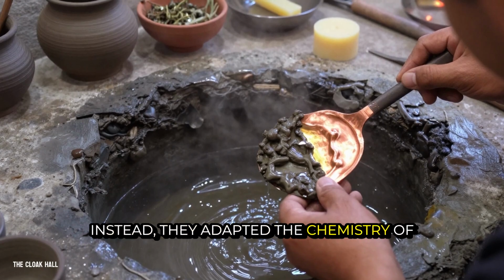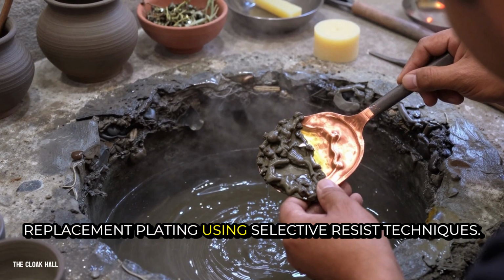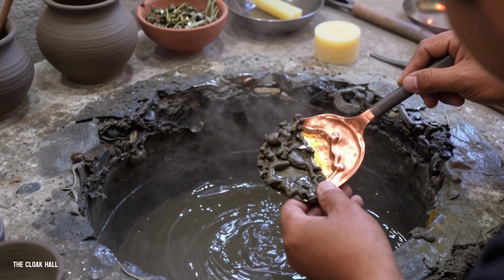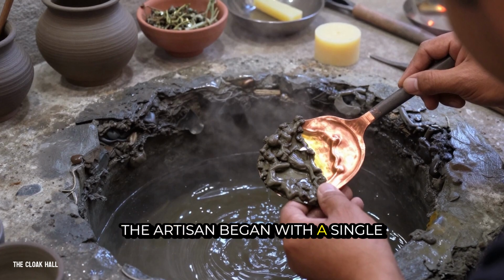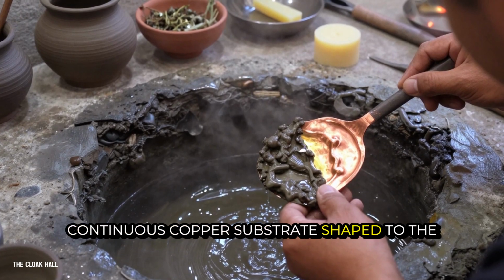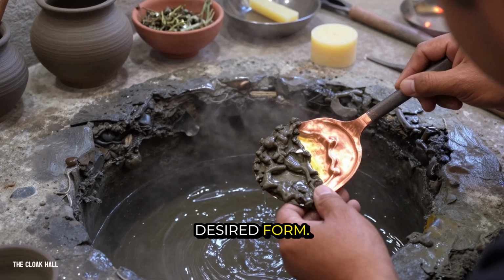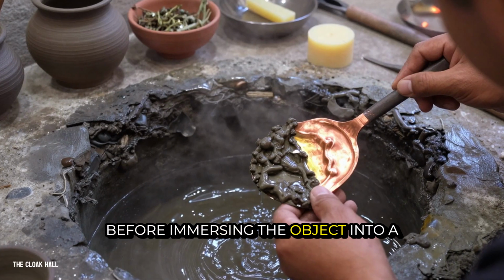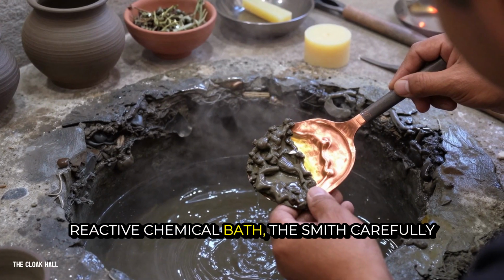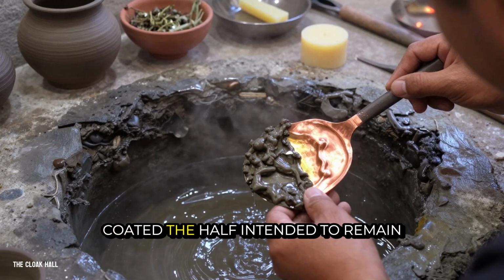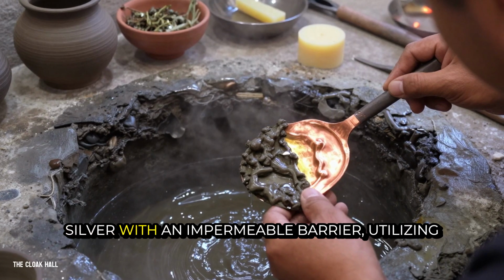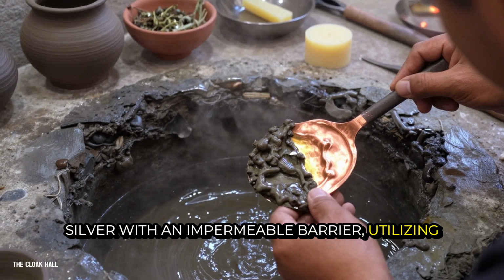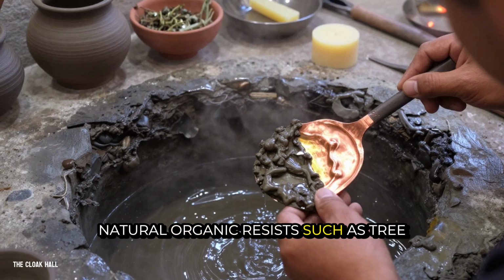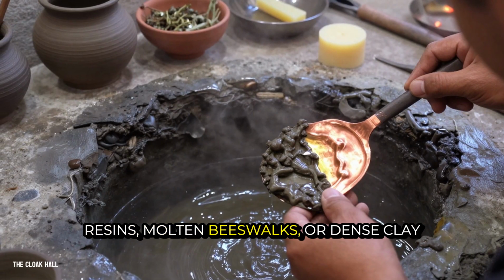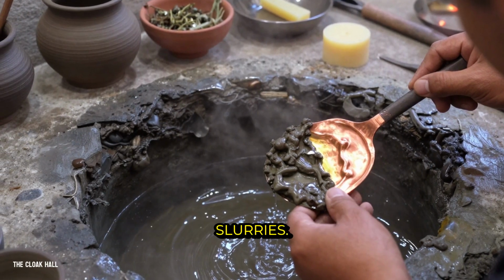Instead, they adapted the chemistry of replacement plating using selective resist techniques. The artisan began with a single, continuous copper substrate shaped to the desired form. Before immersing the object into a reactive chemical bath, the smith carefully coated the half intended to remain silver with an impermeable barrier, utilizing natural organic resists such as tree resins, molten beeswax, or dense clay slurries.